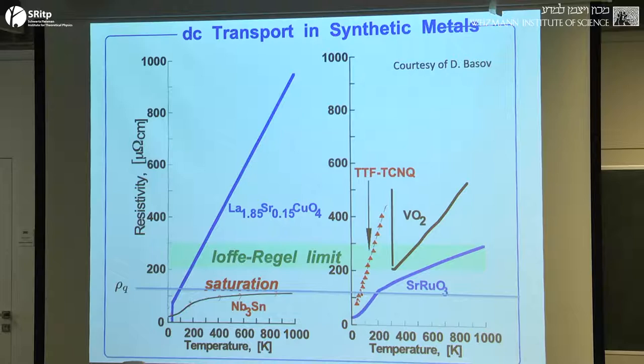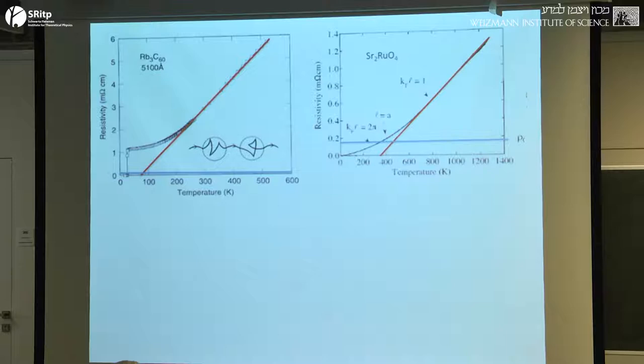I'm actually less confident of how convincing that argument is. Here's the example that I wanted to show you. This is rubidium-3C60, an organic superconductor with a nice high superconducting transition temperature. But what I want you to see is that at high temperatures, it has a T-linear resistivity. And notice this is 1 milliohm centimeter, 2 milliohm centimeters. My quantum of resistance here is now this blue line down at the bottom. So no matter how you play around with 2 pi's, there's just no way this value of the resistance can be understood in terms of Boltzmann transport theory.